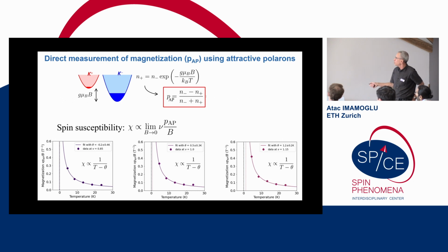So as I already told you, I can look at the strength of the attractive polaron resonances, take their difference, and divide by the sum to determine the magnetization of the system. And from this magnetization, as a function of magnetic field, I can take the limit as B goes to 0 and determine the spin susceptibility. Okay? So at high temperatures, these are what we obtain for different filling factors. And you see that this theta is the Curie-Weiss temperature.